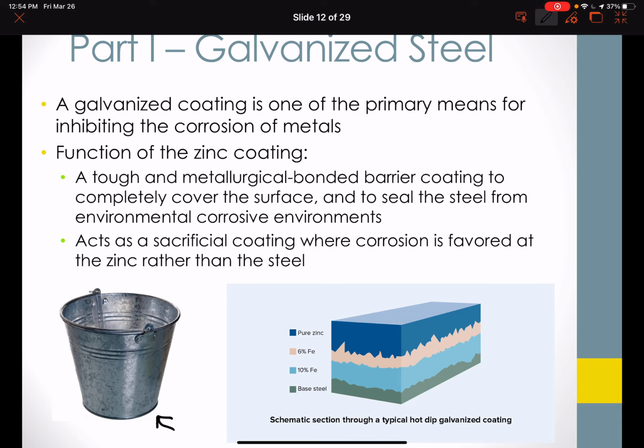So what we see in steel are, as we mentioned a moment ago, often an exterior coating that is pure zinc and the base metal well below it. And often in the interior, we see alloy or intermetallics forming depending on the method. Okay. And so the hot dip method is the one that tends to generate the situation where we have a lot of excess zinc on the surface in the form of pure zinc, as we'll see.